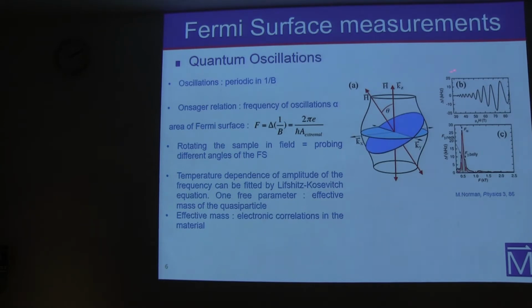So let me go back. First, we look at those quantum oscillations. By taking the Fourier transform, we get one peak, or several peaks if there are several frequencies. And now, the amplitude of the peak actually depends on the temperature. So if we plot the amplitude as a function of temperature, we can fit that curve with a Lifshitz-Kosevich equation. This is a well-known equation for quantum oscillations, and that equation has only one free parameter, which gives you the effective mass of the quasi-particle. So by doing a temperature dependence measurement of those quantum oscillations, we can access the effective mass of the quasi-particle in the sample.